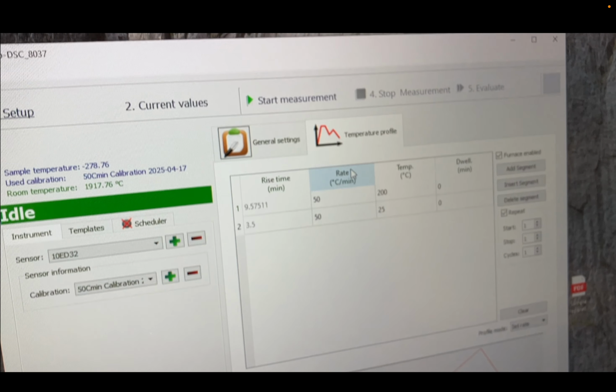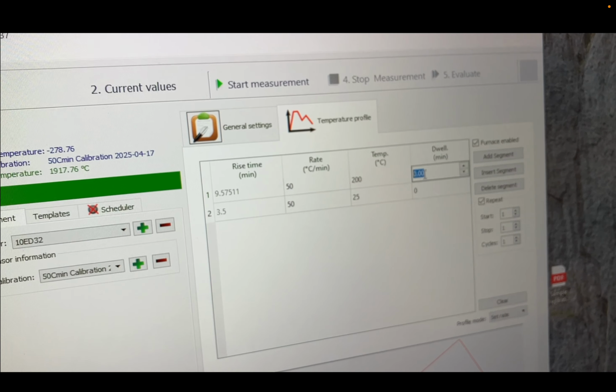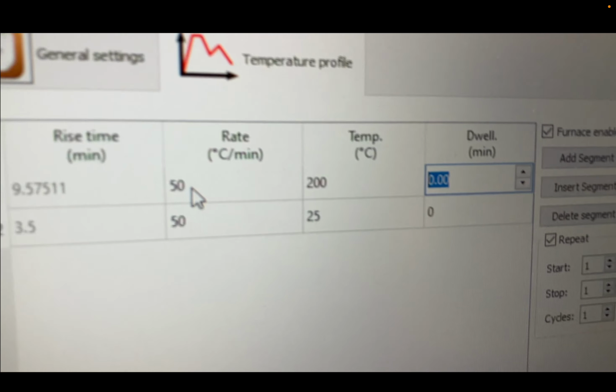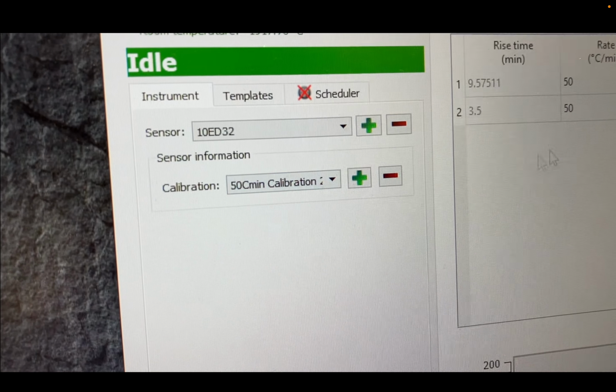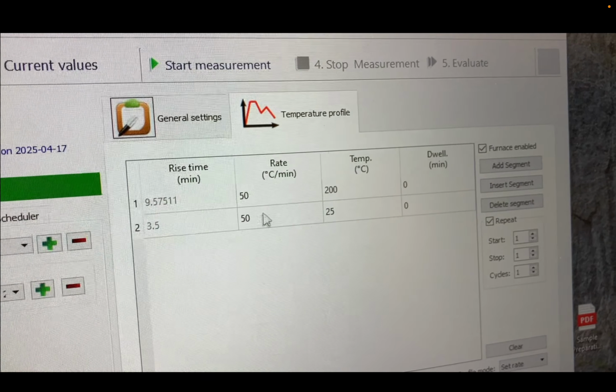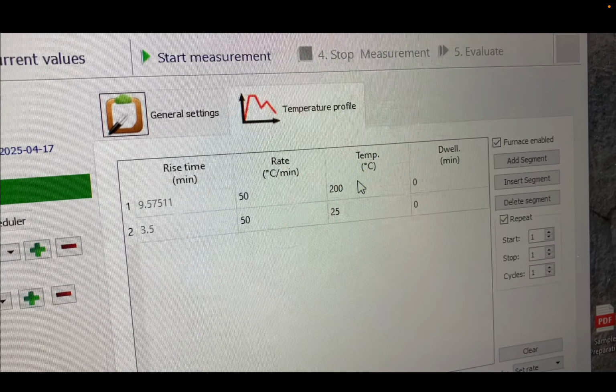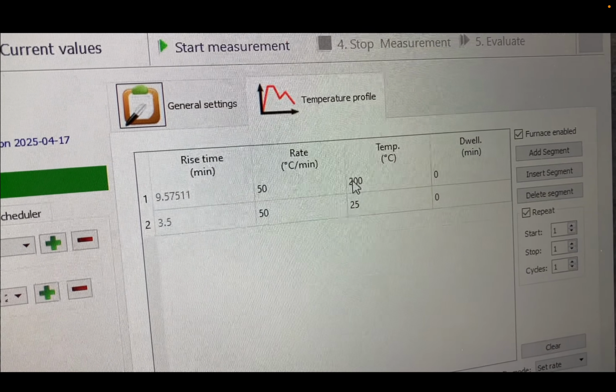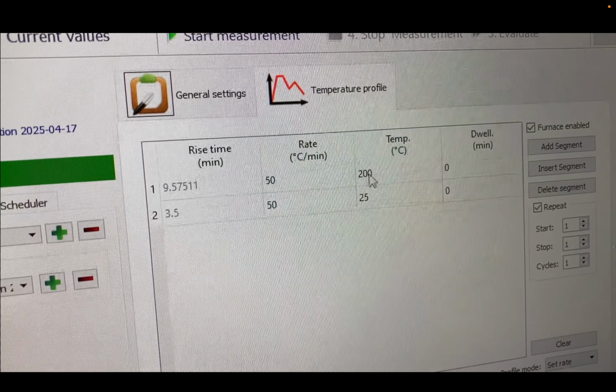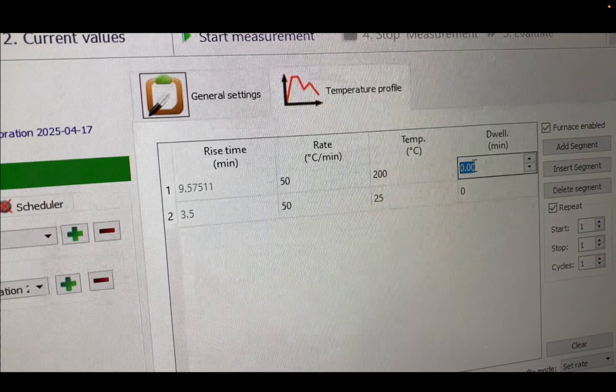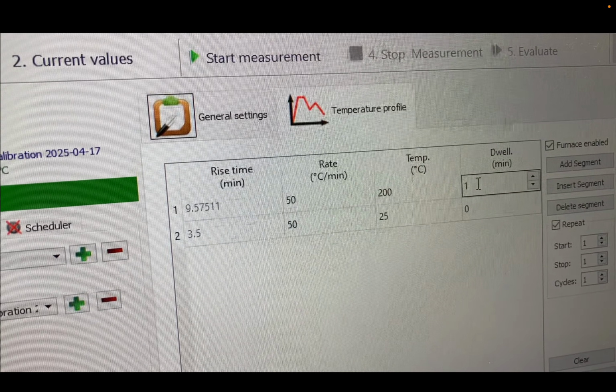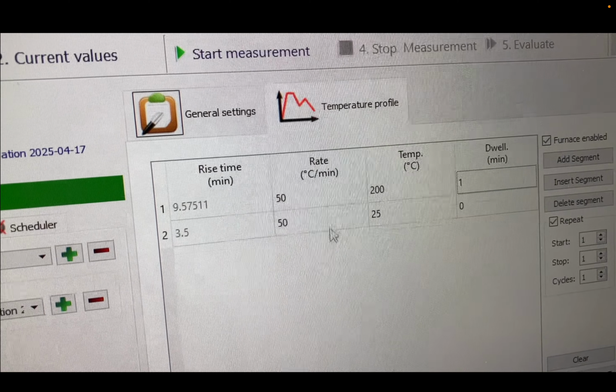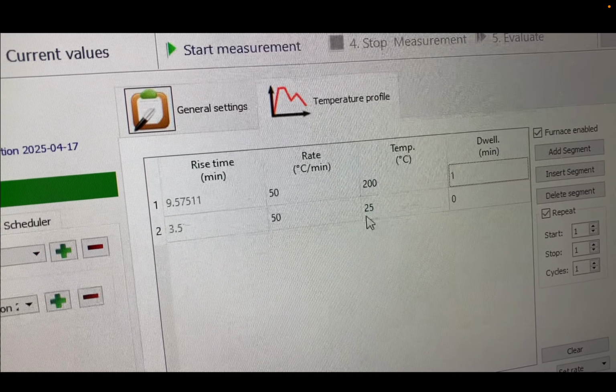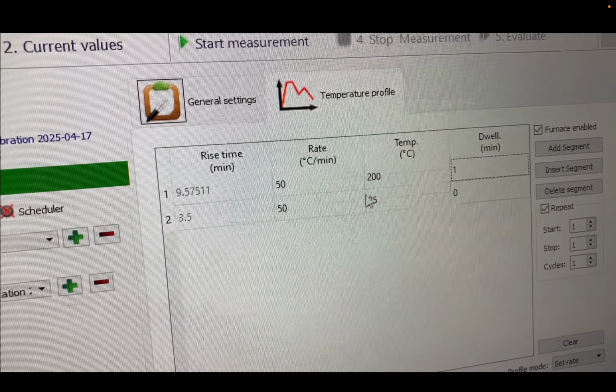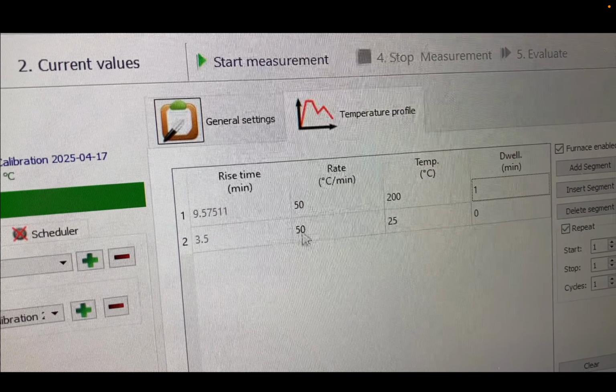And then we go to temperature profile. This is where we'll set the specifics of our test. So you can see the calibration we're using is for 50 C a minute. So all of our rates are going to be set at 50 C a minute, otherwise it won't be accurate. So we'll start by doing 50 C a minute till we get to 200 C. Once we're there, we'll make a 1 minute dwell time, which means it'll stay at 200 for 1 minute. And afterwards, we will cool back down to 25 C at the same rate of 50 C a minute.